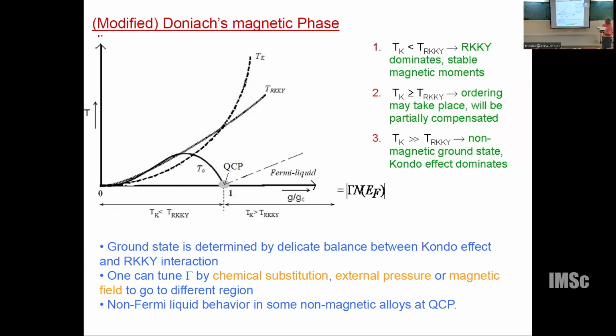At large coupling, basically large hybridization and large bonding, you have an intermediate valence. At weak bonding, you have a stable valence, and you can go from stable valence to strong hybridization. In between, where you are losing magnetism as a function of coupling, very exotic phenomena are discovered, quantum critical points, called quantum critical point effects. This is one of the things attracting a lot of attention.